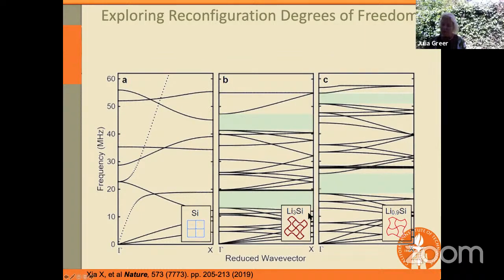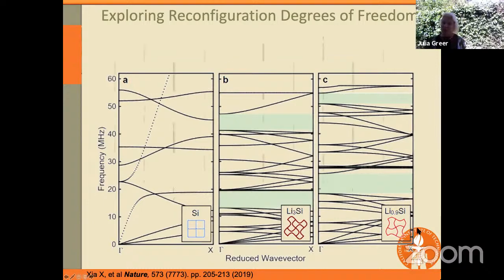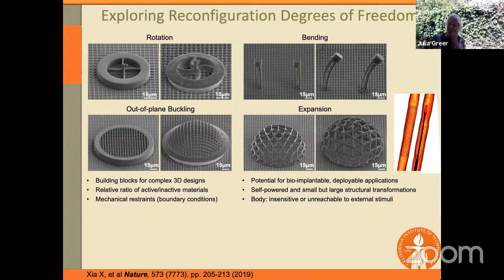But once you start lithiating it, for example, here's a band gap that emerges. And then as you start lithiating it further or delithiating it further, which corresponds to a more relaxed pattern, you can see that these band gaps shift. And so that allows us to attain a variety of different deformations, for example, out of plane buckling or rotation or other degrees of freedom. And that tells us that we can actually utilize these defects to our advantage.